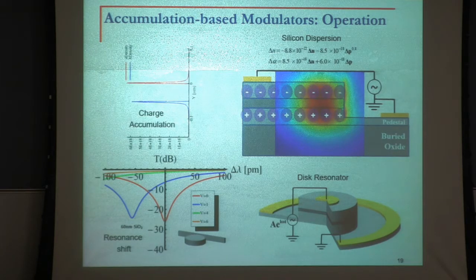Now, the reason we started this is because now I can think about this as a capacitor, as shown over here. Silicon, silicon, and oxide. And by applying a voltage, I can accumulate carriers there without requiring a current. In contrast to conventional ways of using a PN junction and pushing the carriers in or taking the carriers out by a current, I just apply a voltage and capacitively I accumulate the carriers. Now, I apply a voltage as shown here, and clearly I can get a shift. So that's the structure. One electrode is placed at the center of the silicon. The other one is placed at the periphery.